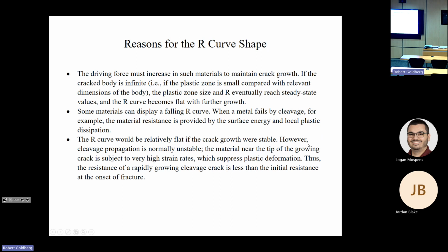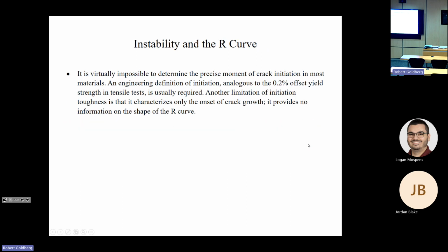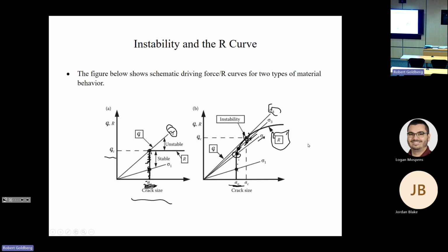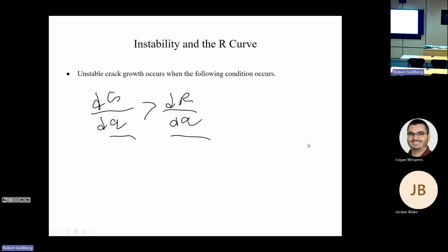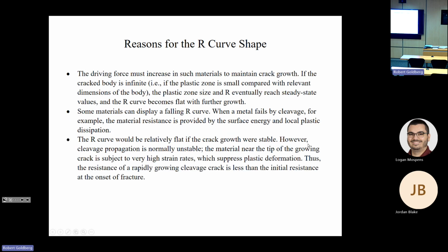So if the cracked body is infinite, what that means is if we have a plastic zone that's really, really small compared to the dimensions of the body, the plastic zone size and the resistance eventually reach some steady state value. Then instead of a continually increasing R curve, it's kind of hinted at here, at some point the R curve reaches some asymptotic value and even goes somewhat flat. And what's even crazier is some materials can display a falling R curve.